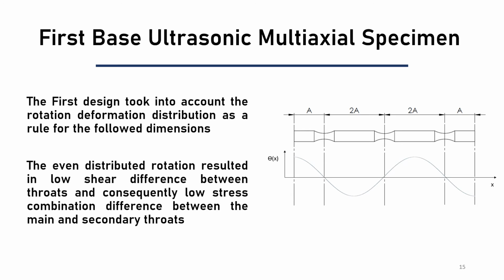The first tested specimen geometry took into account the rotation deformation distribution as a rule for the following dimensions, meaning in the beginning as a quarter wave, meaning A, and then as a half wave, then 2A. This results in an even distribution of rotation deformation and therefore a low difference in shear between the secondary and the main throat, the fatigue testing region.